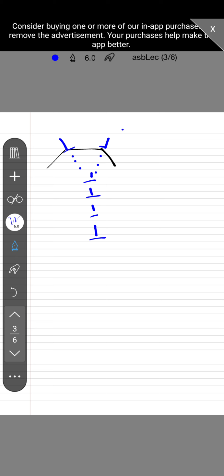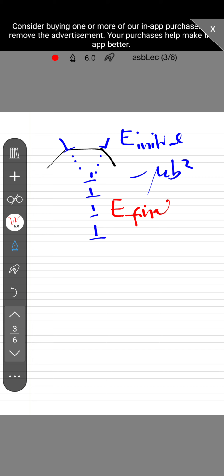So initially there is a reduction of energy. If you consider the initial state with some number of dislocations, the energy is proportional to mu b square. After this localization takes place, that means the dislocations come together and start to form sub-grains, so they align themselves, then the final energy is mu b square by 2.